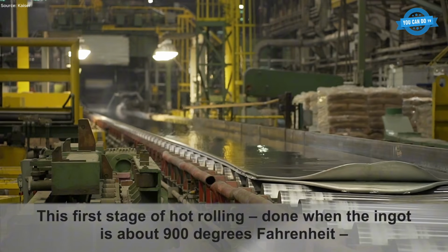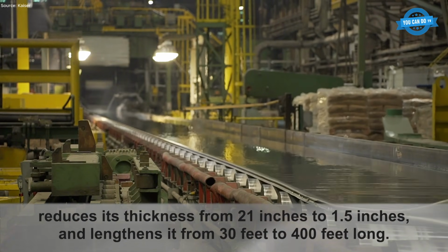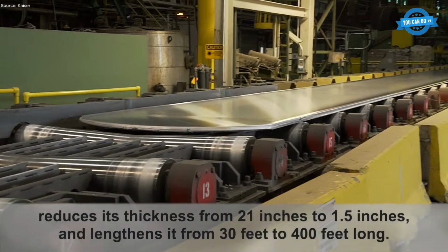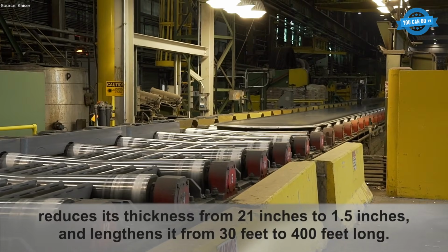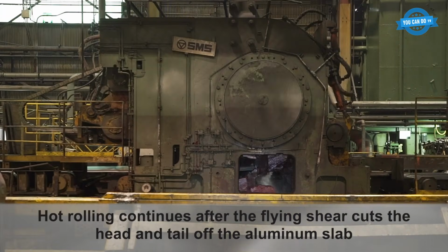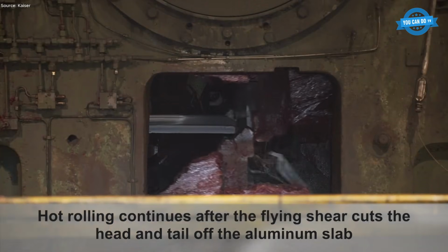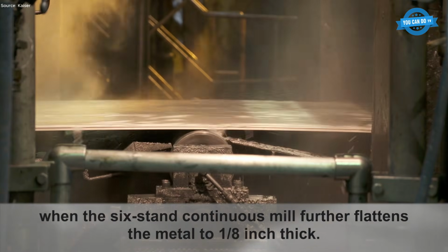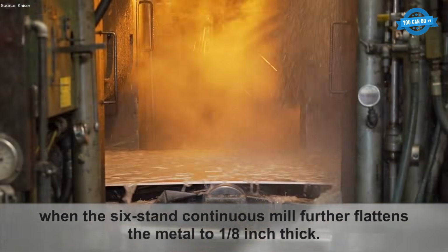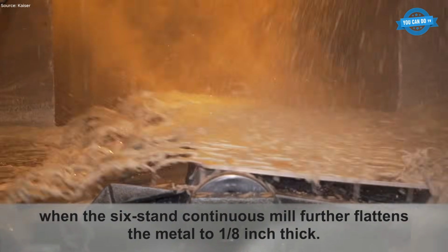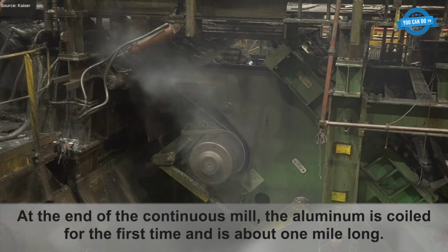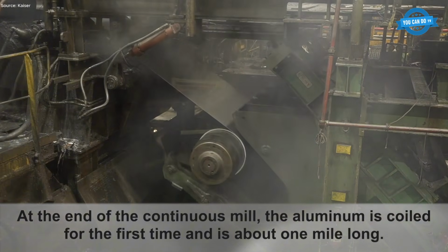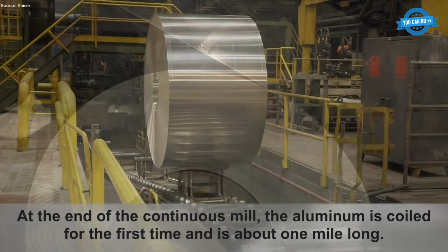Hot rolling starts at the reversing mill, where 44,000 pounds of aluminum pass repeatedly between massive rolls driven by 7,000 horsepower motors. At roughly 900 degrees Fahrenheit, thickness is reduced from 21 inches to 1.5 inches, while length expands dramatically. The continuous mill refines it further before coiling. Cold rolling follows, bringing final gauge accuracy measured in thousandths of an inch.